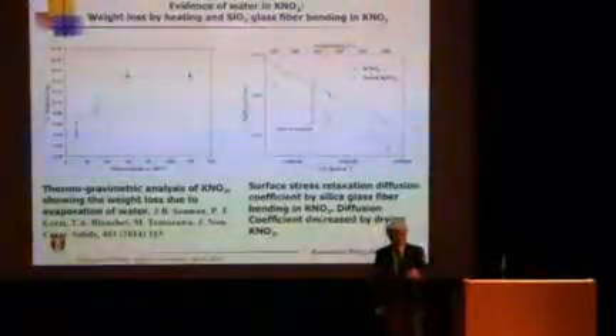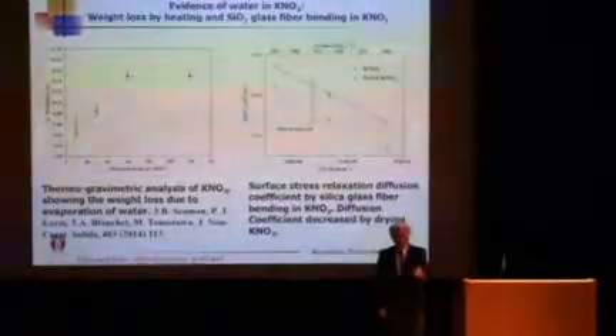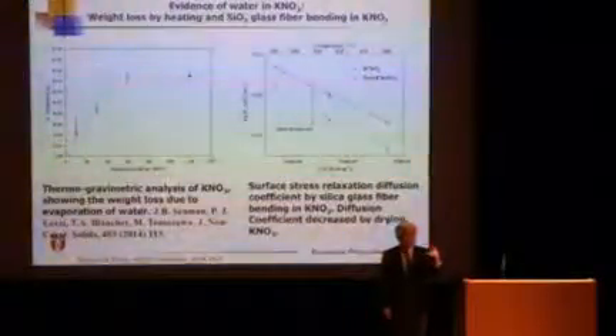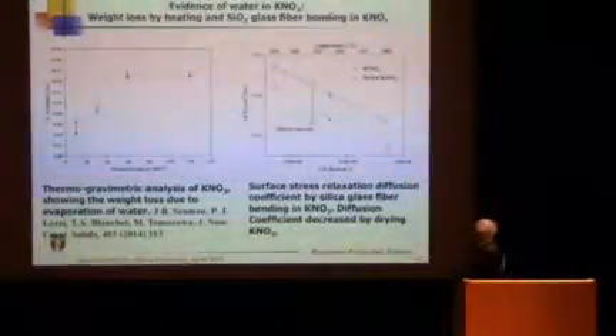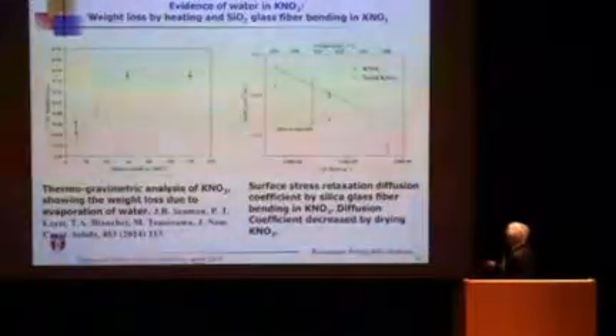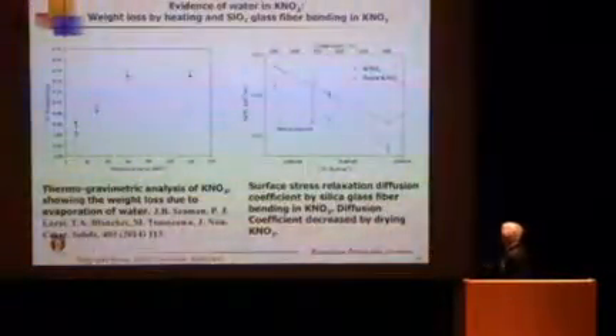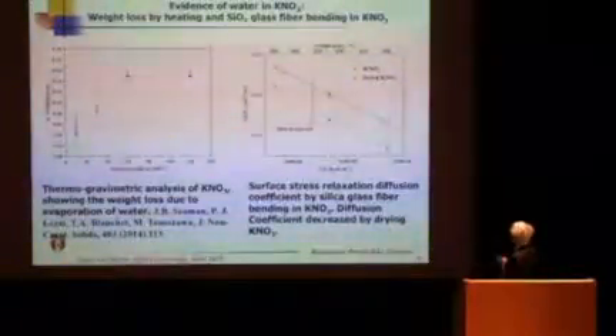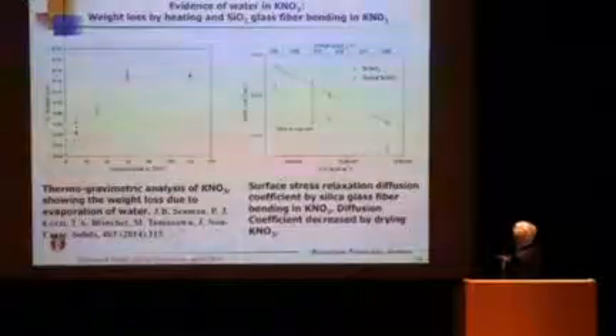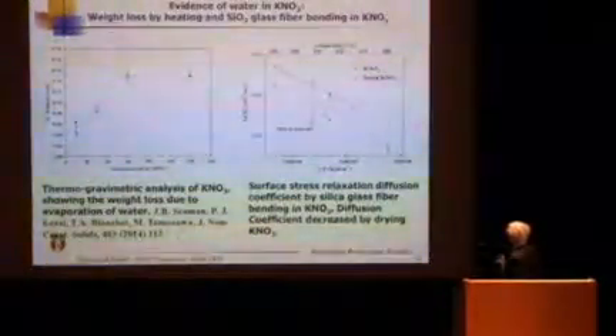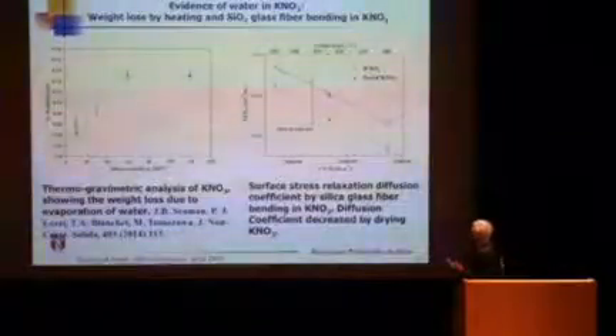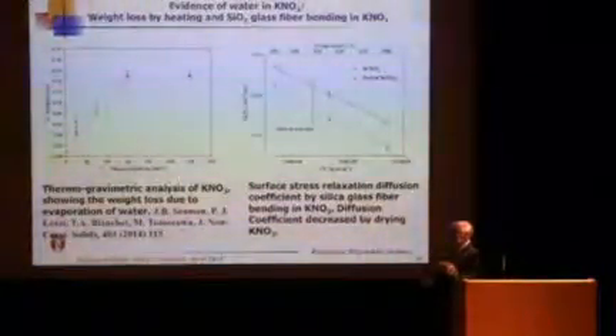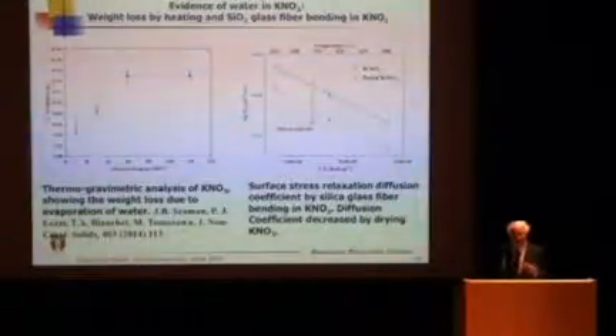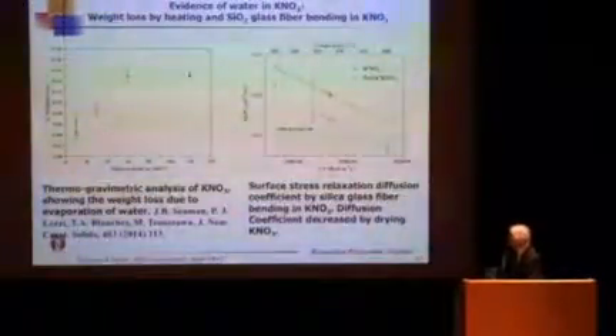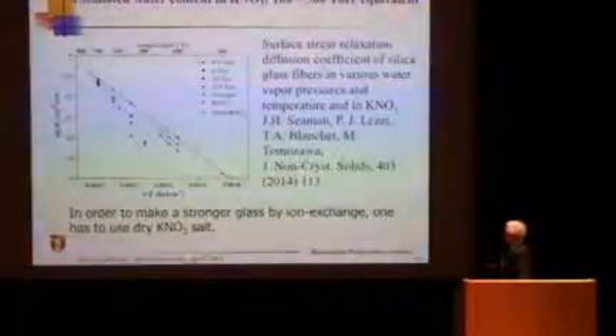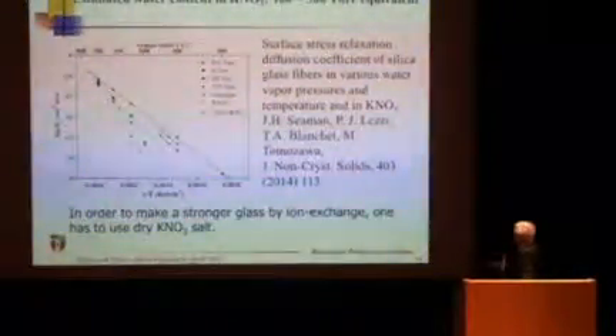Silicon glass fiber was immersed in molten salt and bent, and then taken out to see how much bending took place for a given time and temperature. From that we got the surface stress relaxation diffusion constant of silicon glass. So this one is before drying, after drying. By drying, it dropped. So certainly, whatever it is, we are evaporating. After evaporation, it's happening much less. So we believe water vapor is escaping, and that produced this relaxation diffusion constant in molten salt.